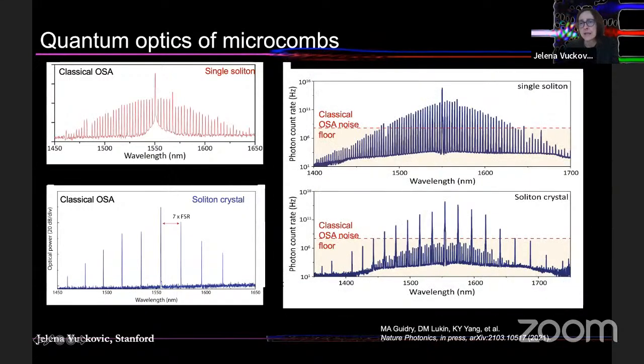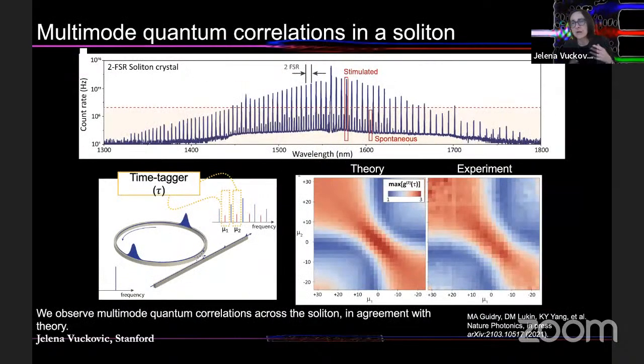And we've also recently looked into subthreshold behavior, both of single soliton and soliton crystal, by building a single photon optical spectrum analyzer. We looked below the classical optical spectrum analyzer noise floor with this instrument. And we were very excited to see in the soliton crystal these additional lines that occur as a result of the frequency mixing of the soliton crystal lines. This is interesting because it's really looking deeper, using tools and techniques that we have from quantum optics, into the behavior of soliton combs. But potentially it also has some applications in quantum optics, because in some special regimes of operation, you can observe a massive entanglement between the spectral lines in these soliton combs. We're not really there yet because we have to redesign the structure in order to preserve the entanglement at the output.